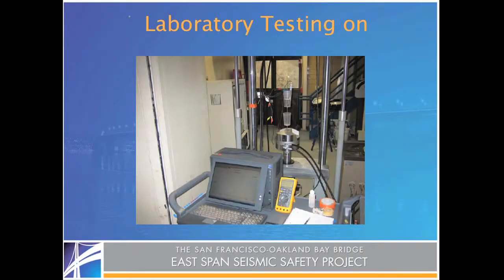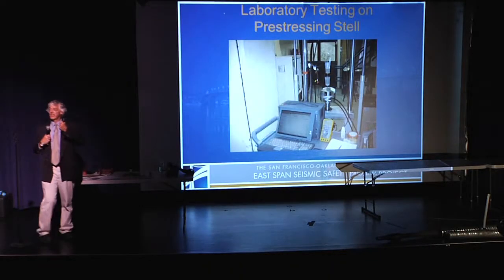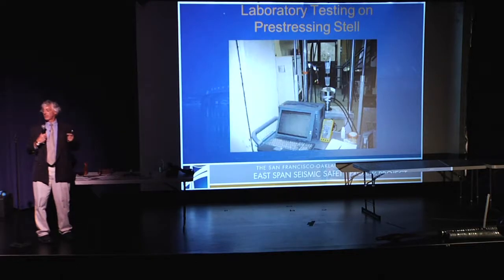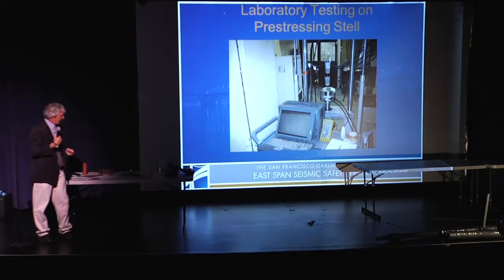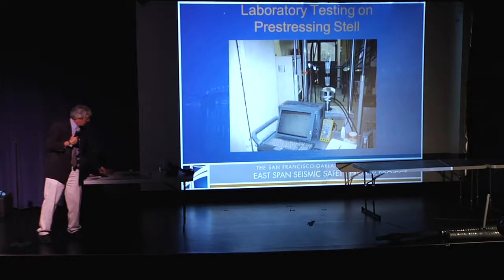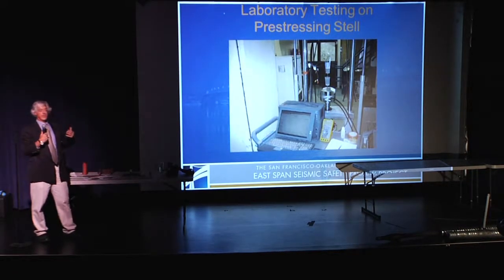Okay. We even set up a lab experiment and test. It's a test, not an experiment. It's a test where we actually took some of those tendons and we held them under stress, right, in their conditions, because corrosion is made worse by stress. Okay, so we did quite an evaluation. Okay, so quite frankly, with the peer review panel looking over our shoulders, we put a team together as soon as it was discovered. We got as much information as we can. Sometimes we even went out and purchased new equipment that, quite frankly, perhaps at this point had never been used for anything quite like this before, to allow us to collect overwhelming evidence.